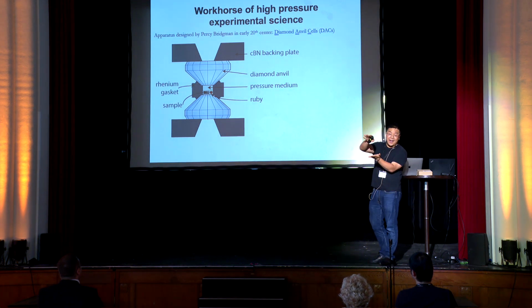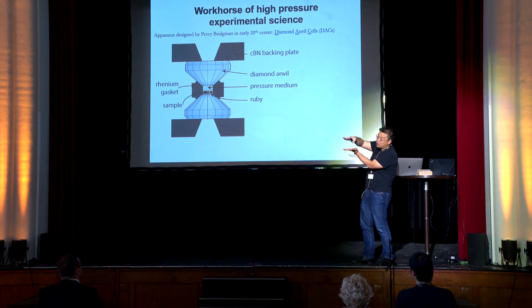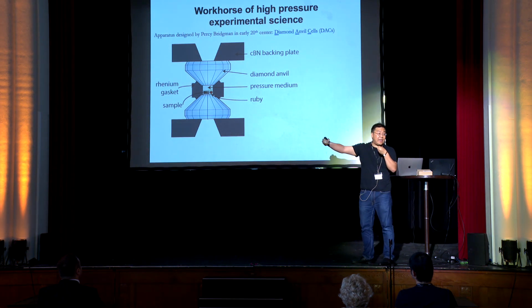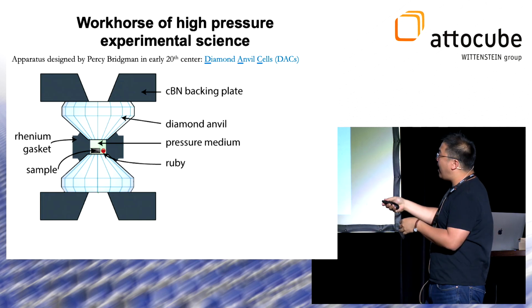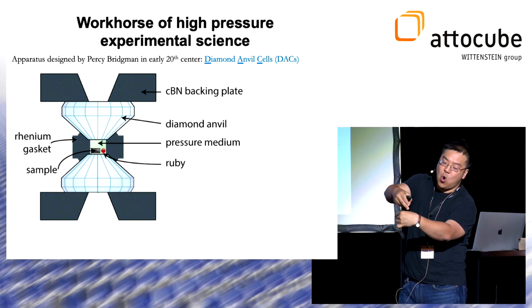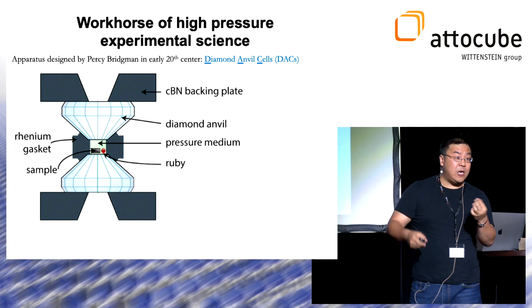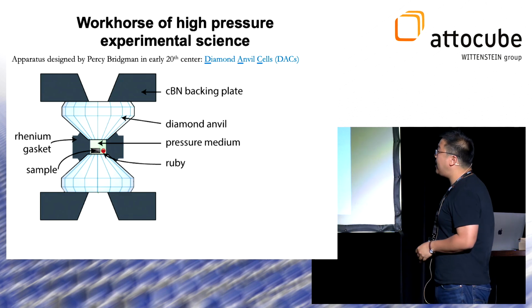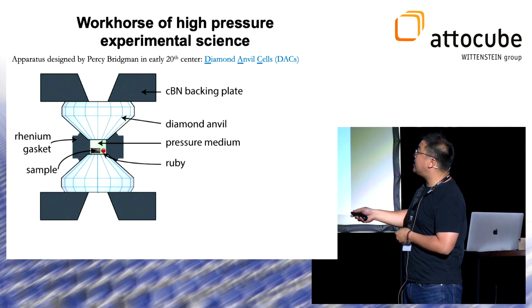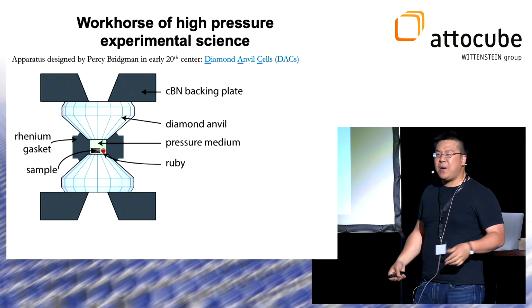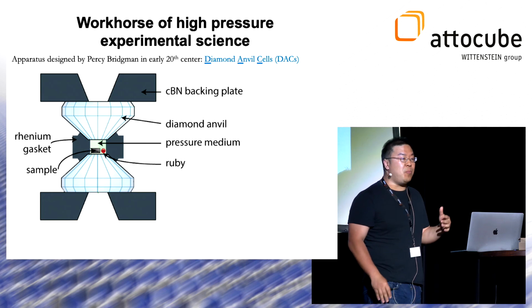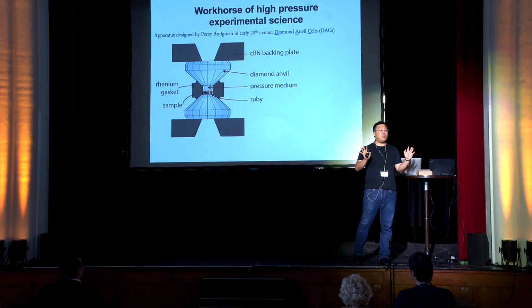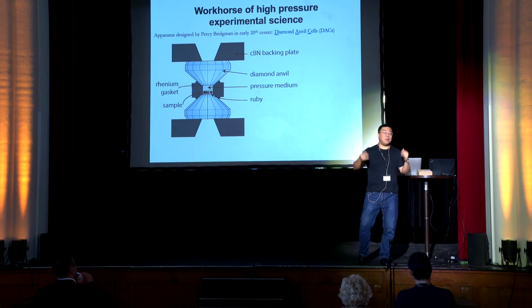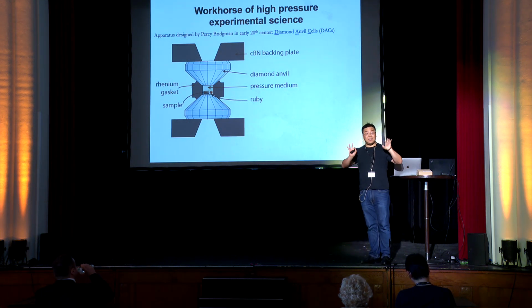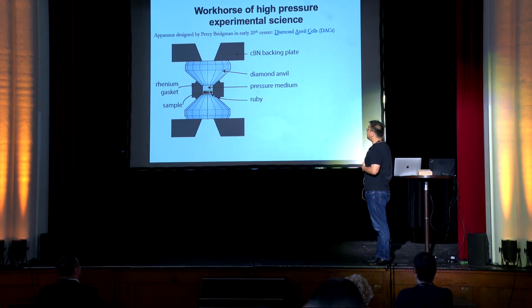You know that if you stuck a piece of Play-Doh between two anvils and you squeezed, or a material in general, it would typically expand out the sides. So to prevent that from happening, in this cross-sectional view, you have a little bit of an O-ring that surrounds the sample chamber to make sure that the sample doesn't actually get squeezed out of the sides. And in addition, inside the sample chamber defined by that O-ring, typically you have either a gas or a liquid pressure medium to try to make the pressure and redistribute it as hydrostatically, as spherically symmetrically as possible. So that's the basic setup that we're working with to apply high pressures in quantum material systems.